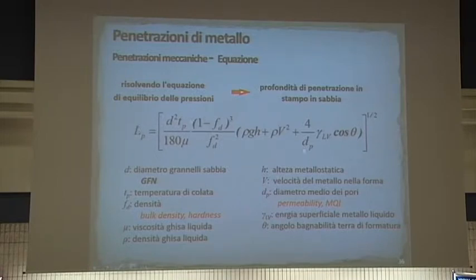And you can see the variables. Here are all variables that you can relate to the foundry. So it's GFN, the diameter of the grain, the pouring time, the fraction of grains, which is bulk density or hardness of your mold, the viscosity of your liquid metal, density of the metal, metallostatic pressure, height of the mold, velocity of the metal coming into the mold, and again the grain density, the grain size. So these are all, we translated all these physical parameters into parameters that you measure in the foundry.